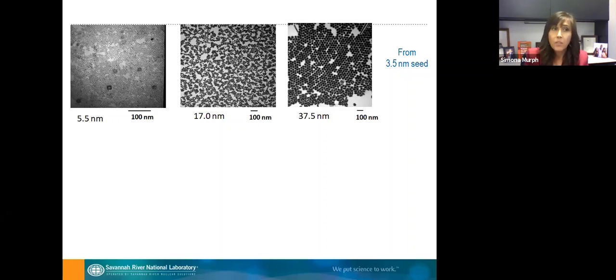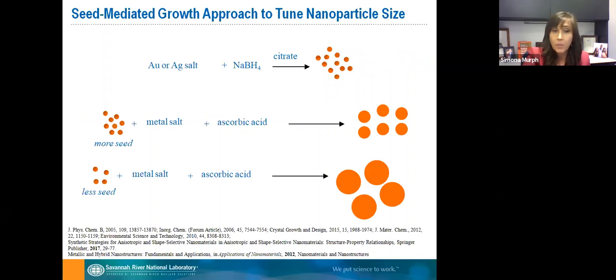The more you increase and use this procedure, of course, the more dispersed the medium is. So we have to balance this, how far you can push the size. And once you create them, of course, you have to try to separate other shapes from the rod nanoparticles. But if you look back at the seeds, you can have the seeds of one material, for example gold, and use a different metal salt. You can use, for example, platinum or palladium, and you can create these hybrid materials.